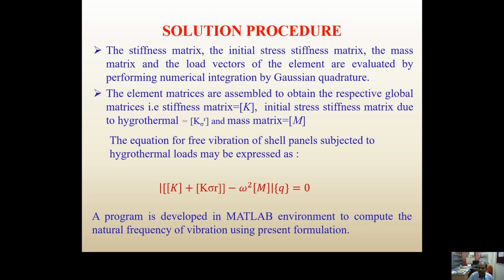Stiffness matrix K, this is the bending stiffness. The initial stress stiffness matrix due to hygrothermal loading, K sigma R or K sigma n, and mass matrix M. The equation for free vibration of a shell panel subjected to hygrothermal loads may be expressed as K plus K sigma R, these are the extra terms coming for hygrothermal loading, minus omega square M, times q, is equal to 0. This becomes an eigenvalue problem.